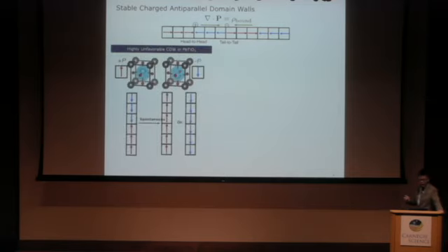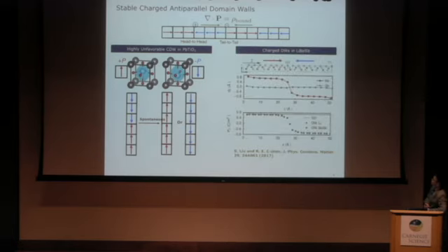And this is indeed the case for conventional ferroelectrics like lead titanate. So even in a computer, essentially at 0 Kelvin, we can start with a configuration with charged domain walls. But during relaxation, it will spontaneously transform to these single domain configurations because this configuration is not even metastable. So we carried out first principles density functional theory calculations in lithium, beryllium, antimony, and this is a hyperferroelectric.